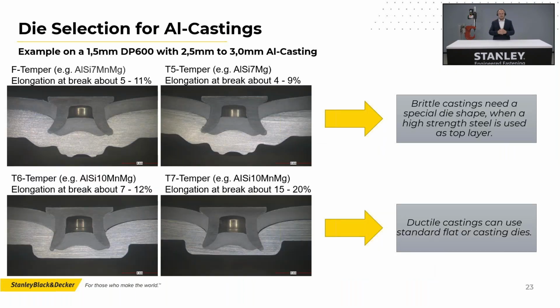On the next picture, on the next slide, let's say, you can see some examples. So in these examples, we used a DP600 to a 3 millimeter aluminum casting, and we used different castings. You can see the alloy information, ALSI 7, ALSI 10, and the first picture is F-temper, meaning no heat treatment, elongation between 5 and 11%. The next one is T5 temper, and interestingly, T5 is worse than F because the elongation is even lower. So for those low ductile castings, brittle castings, we use the special casting die. And then if you have the more ductile castings like the T6 and T7 ones, we can use the flat dies, and all of these results that we show are without cracks. So these are all okay joints that can be used, that can be run in the car, on the road, in your production. Nothing will fail, okay?